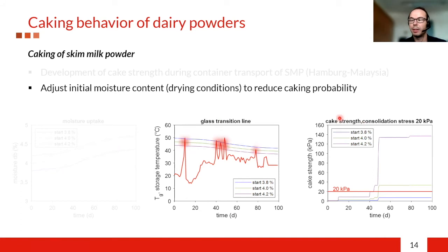You can see here on the right side the cake strength at a consolidation stress of 20 kilopascal, how it developed. You can see that for the low moisture content SMP, there is no caking at the end, so everything is fine. But for the higher moisture content at 4% and 4.2, we have lump formation. For the 4.0% moisture content, lumps were formed or can be expected to be formed at 50 days of storage. And the highest moisture content, the powder arrives as a massive block at the customer, who will not be very happy with this one, I think.